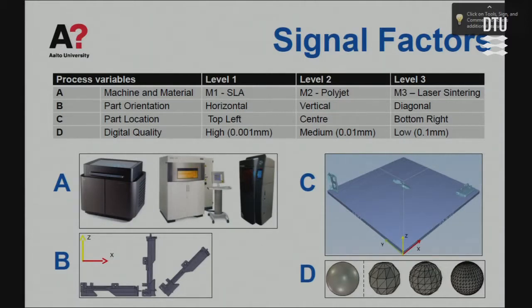Then it was the part orientation, meaning that you have different resolutions in different axes. The most accurate plane is XY, and then you have less accuracy in the Z direction. So I printed parts horizontal, vertical, and diagonal at 45 degrees to the XY plane.